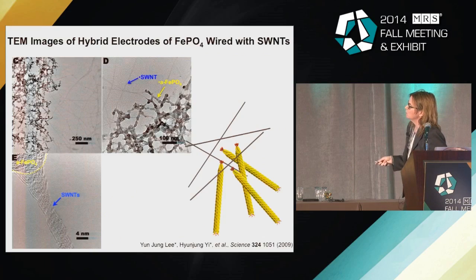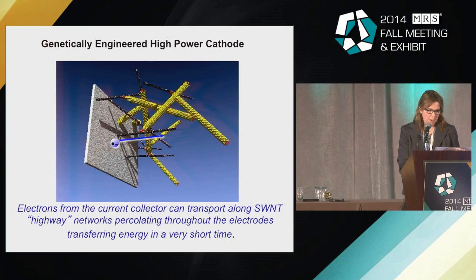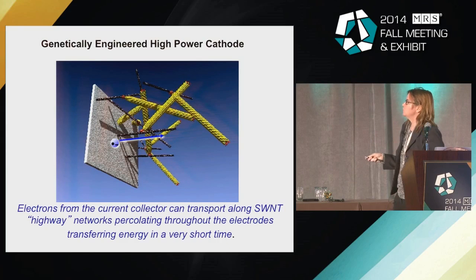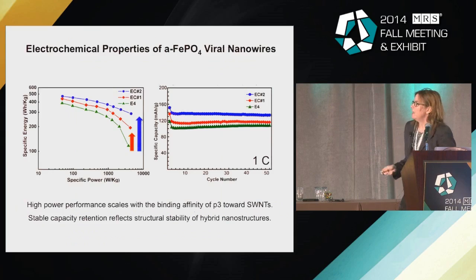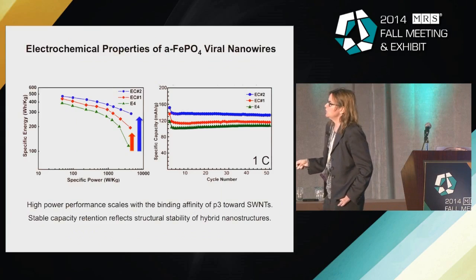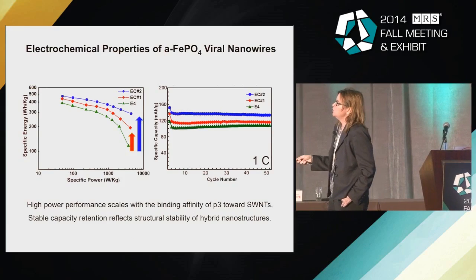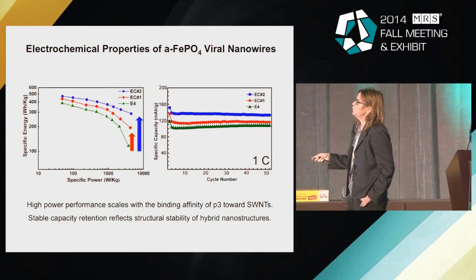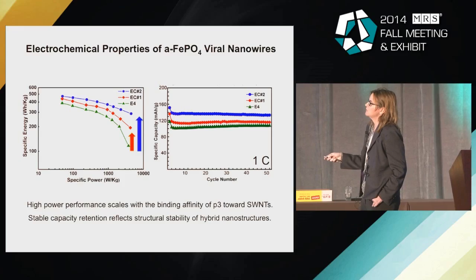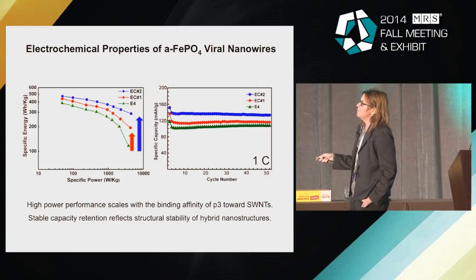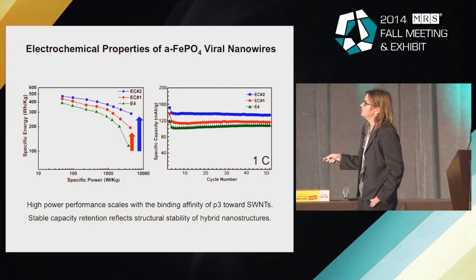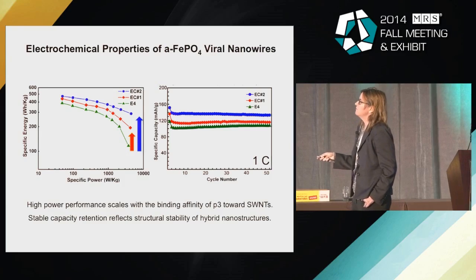And this is a TEM image of what it looks like. They can form a percolating network of these virus CNT complexes that are now mineralized with the cathode material. Basically, what happens is it forms a superhighway to get electrons through this percolating network and transfer energy in a very short period of time. What we found was that this is specific energy now versus specific capacity. This is a 1-gene battery. This is a 2-gene battery, and this is our best 2-gene battery. It has the best DNA sequences that bind the carbon nanotubes the tightest and are very effective at growing the iron phosphate material.